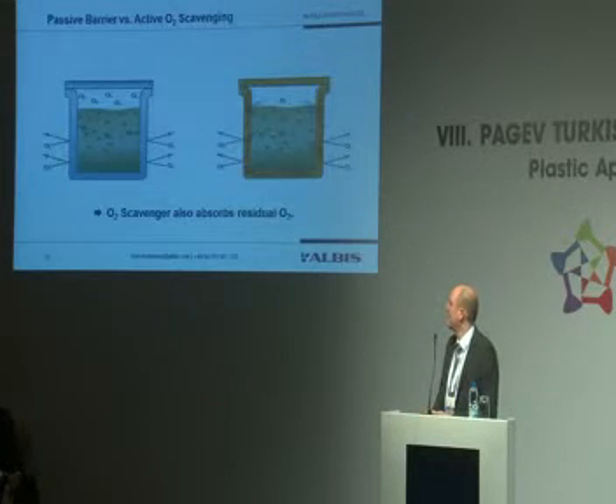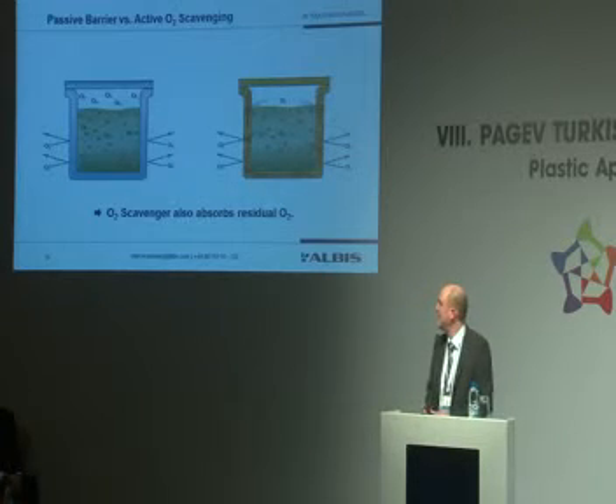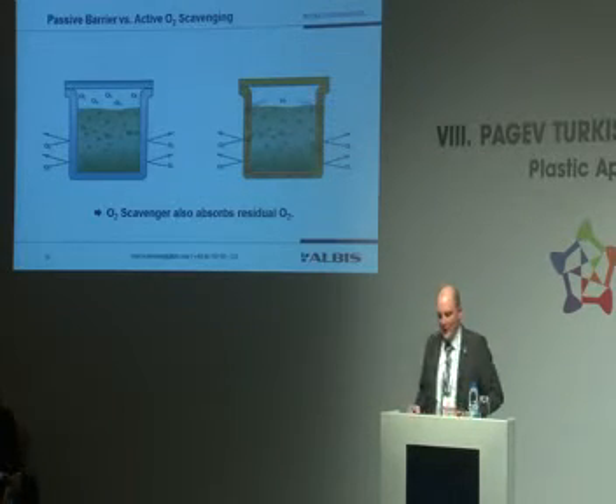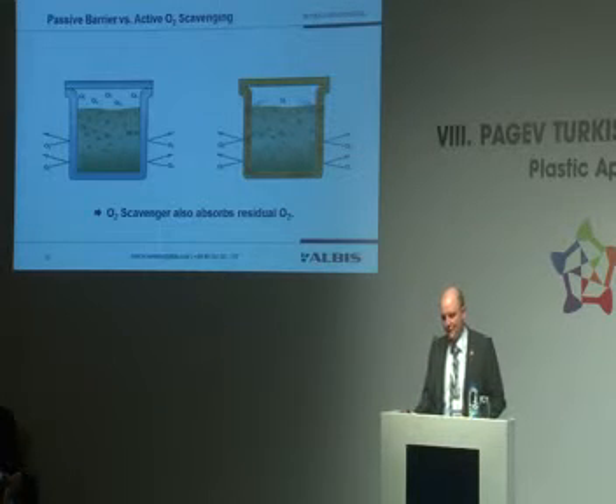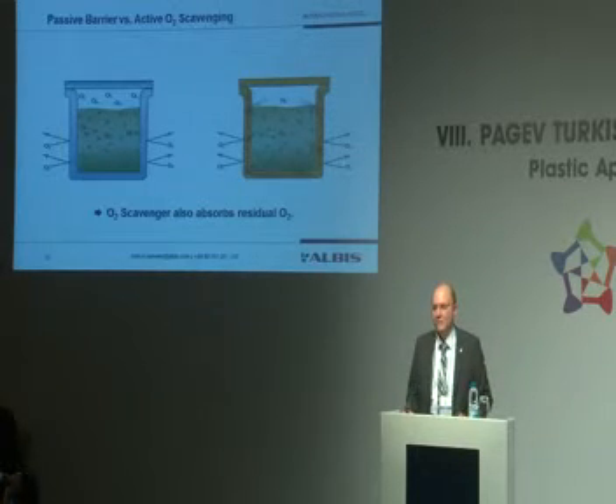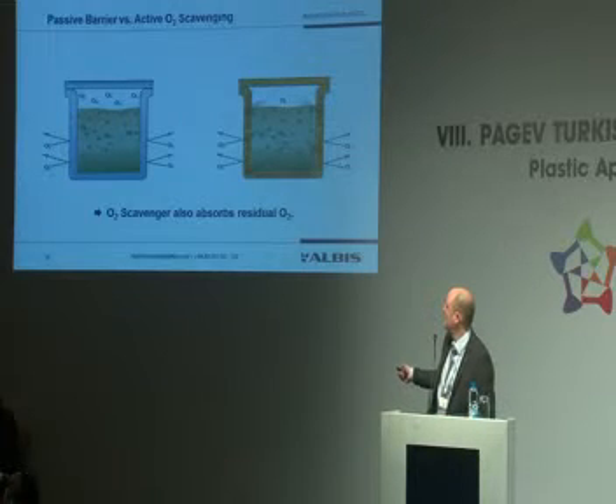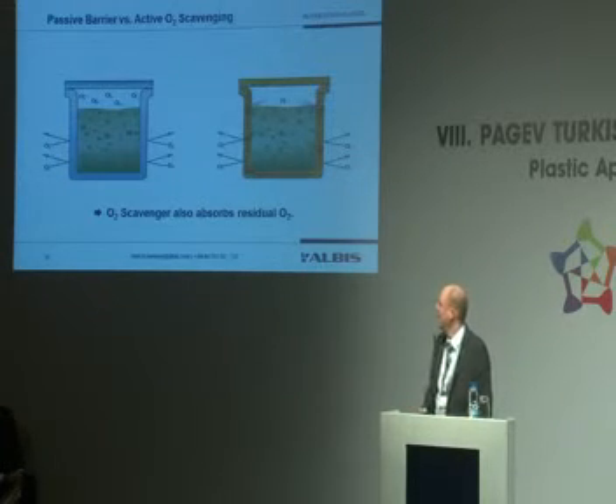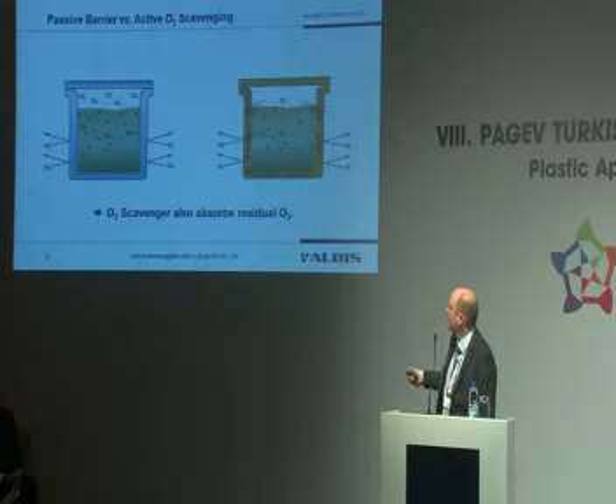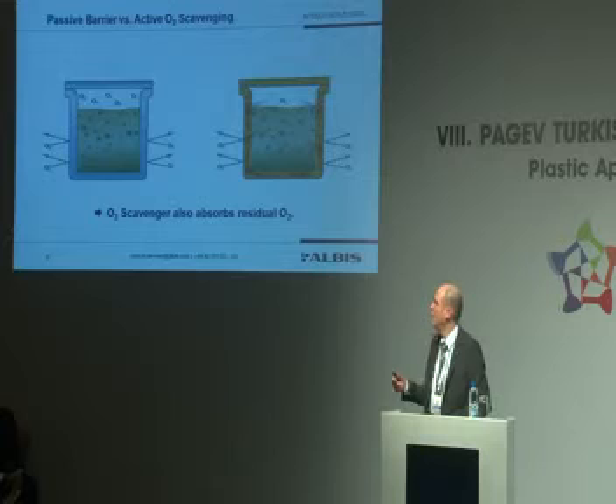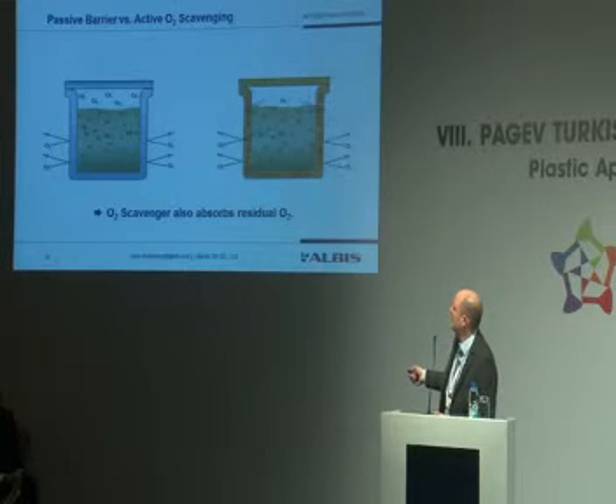Now, how does this work in a little bit more detail? On the left-hand side of this slide, you can see what will happen if you apply a passive barrier packaging. You have the packaging thickness, you have the barrier material, for example, EVOH, and you have inside your packaging a certain concentration of oxygen. In the headspace, this can be a high value or a low value, depending if you do MAP packaging or not. And you can also have oxygen inside the food itself. Now, what the passive barrier is doing, it simply blocks any oxygen from going from the outside to the inside.